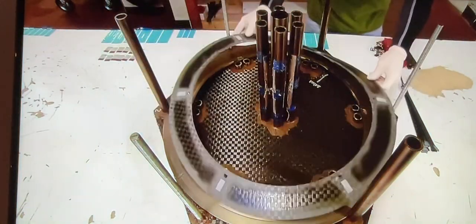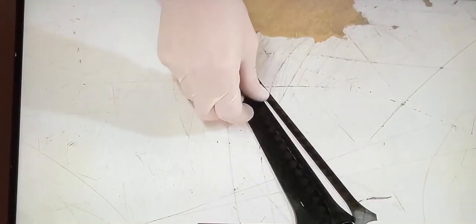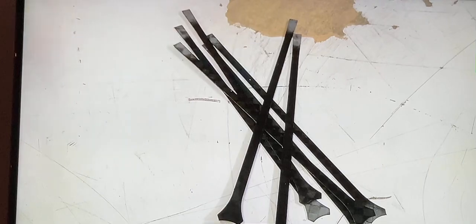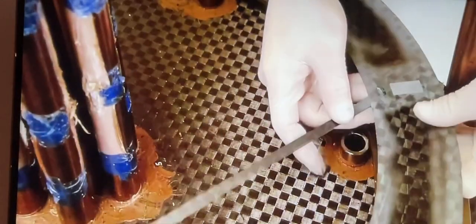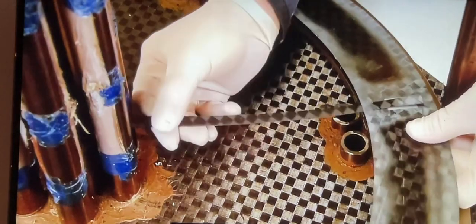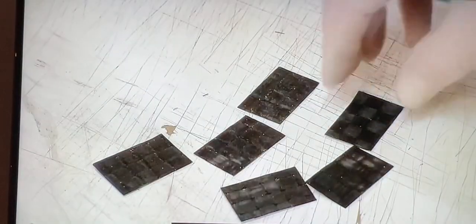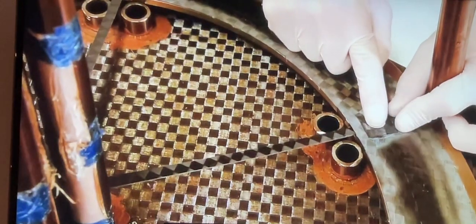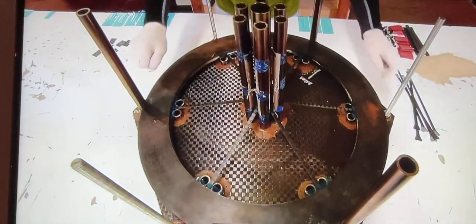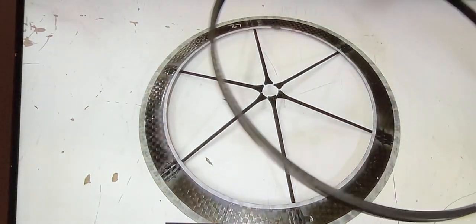They'll now assemble the wheel. The technician inserts flat carbon fiber spokes into holes in one half of a sidewall. Adhesive and carbon fiber will bond the spokes to the sidewall. He places a carbon fiber patch where the end of the spoke meets the sidewall and tapes it there. With all the spokes in position, he lowers the lid and applies mechanical pressure. The spokes bond to the sidewall and it's ready for the rim.